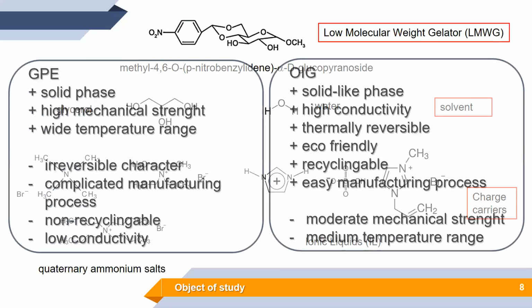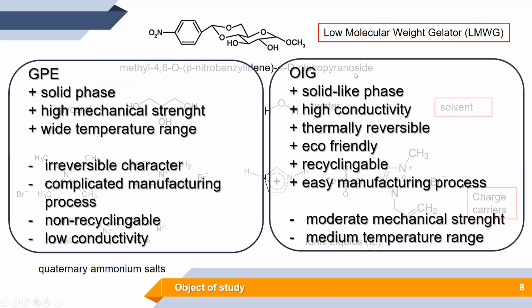And what are the advantages of the, let's say, ionogels based on low molecular weight gelators? They have a solid-like phase. They are highly conductive. As I will show you later, the conductivity is on the level of liquid electrolyte. They are thermally reversible, eco-friendly, and they are very easy in manufacturing. In case of polymer systems, a lot of effort needs to be put in order to get good quality polymer electrolyte and contact with electrodes. In case of ionogels, this is not so crucial an issue, as when it happens that the connection between the electrolyte and the electrodes is bad, we can just heat it up and then cool down to repair this situation.